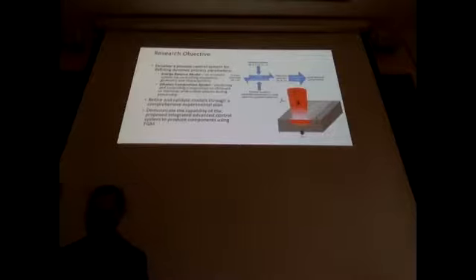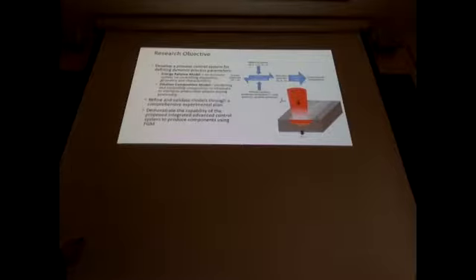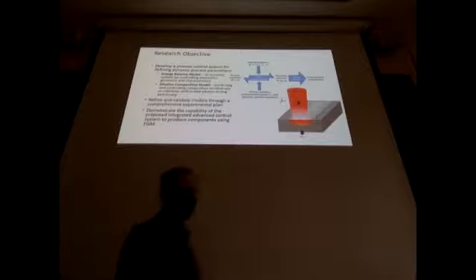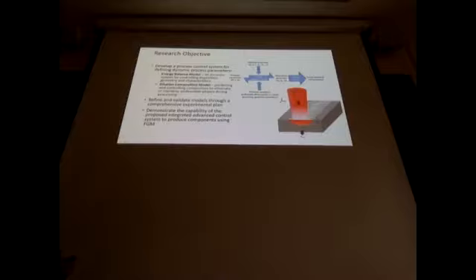And then our objective is to build two models. One is just a simple energy balance model shown here on the right. I don't want to go too much into this, but the idea is that from the power coming in, your efficiencies, and your heat capacities and conductivities, you can get a sense of how deep your melt pool is going to be, and how large your melt pool is going to be, using these constants for the powder. And then all you do is change that depending on what you're trying to change. So if I'm having aluminum and I'm adding titanium, I just modify these density, heat capacity, and thermal conductivity as needed. And then hopefully I can use this as a predictive tool to help understand how I need to run my process. What power do I need to run? What speeds do I need to run? And what should my powder flow rate be?